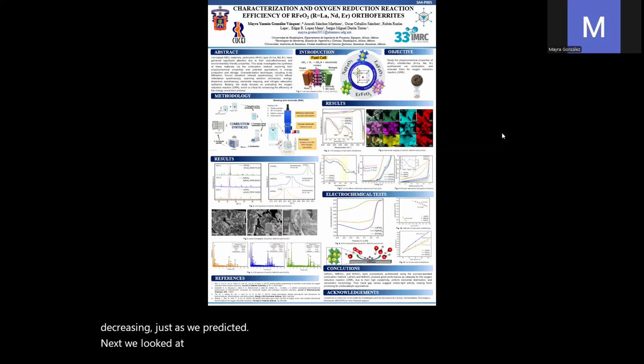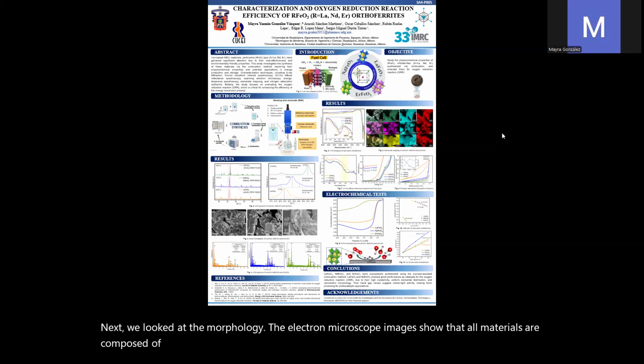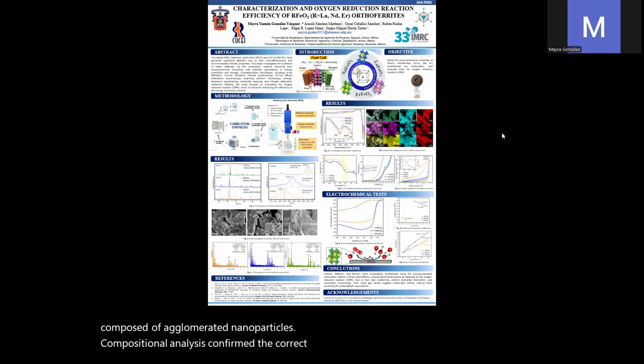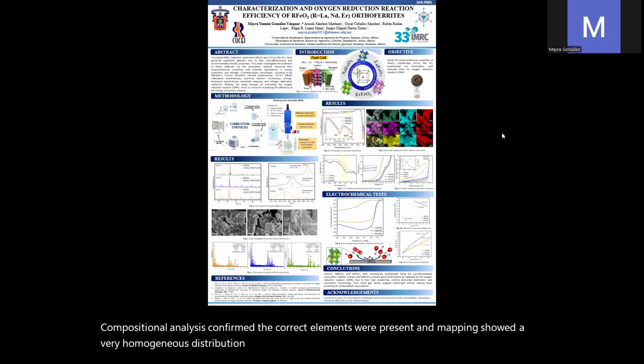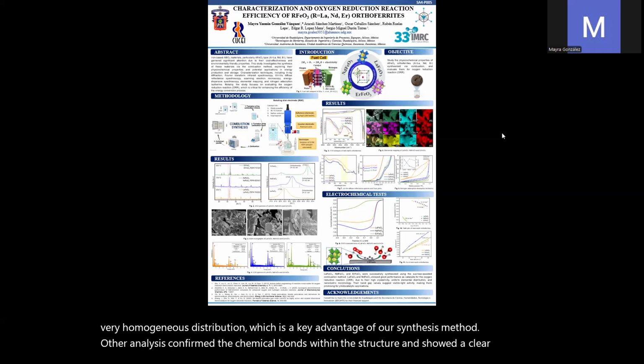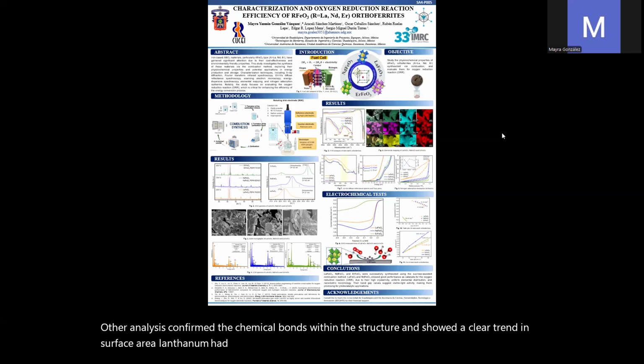Next, we looked at the morphology. The electron microscope images show that all materials are composed of agglomerated nanoparticles. Compositional analysis confirmed the correct elements were present, and mapping showed a very homogeneous distribution, which is a key advantage of our synthesis method. Other analyses confirmed the chemical bonds within the structure and showed a clear trend in surface area. Lanthanum had the highest, followed by neodymium, and then erbium.